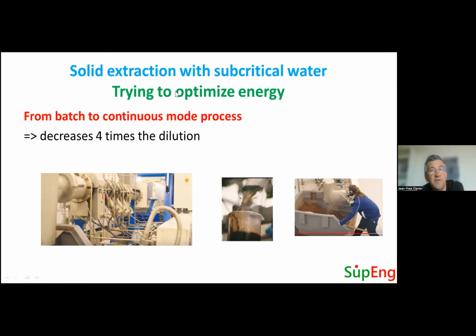So again, we try to develop continuous processes. And here, as we have lower pressure, the pressure in the subcritical water can be typically between 5 and 20 bar. So it's easy to use extrusion-like extractors where we push the feed with screws. This has the advantage of a lower dilution. We can also press the cake of solid at the exit of the extruder, and we can therefore minimize the dilution. We obtain dilution factors of about 4 times, and this makes the process much more attractive.